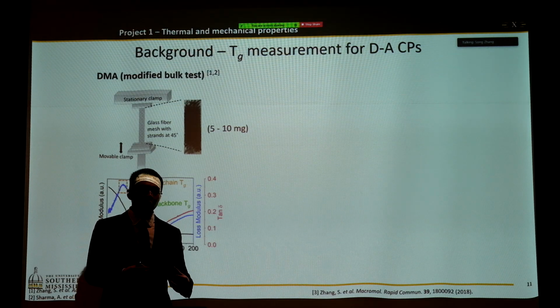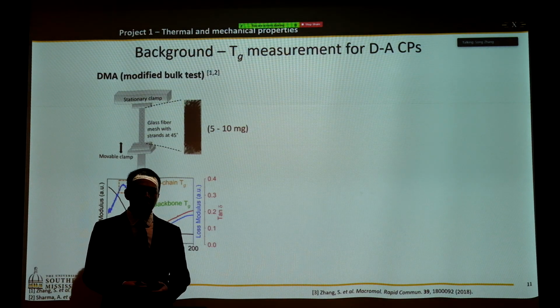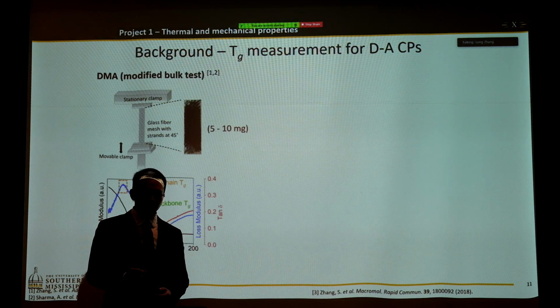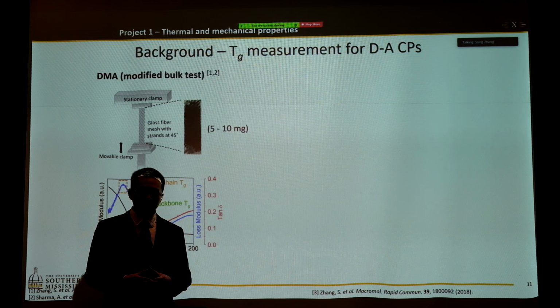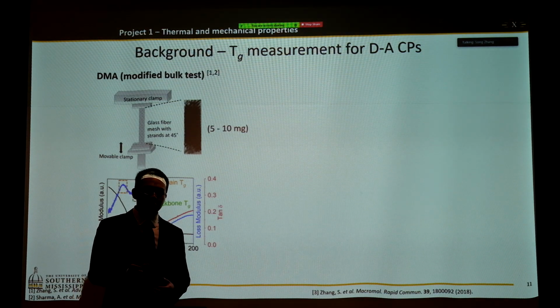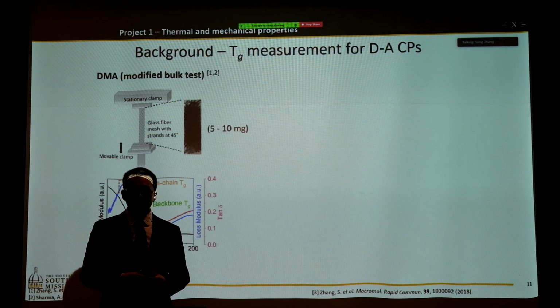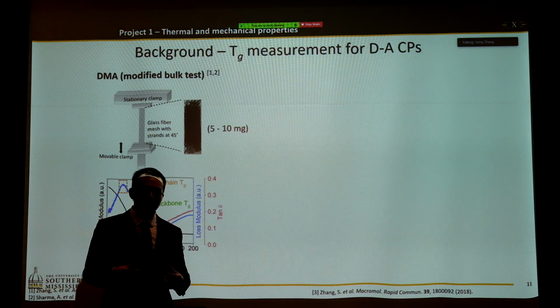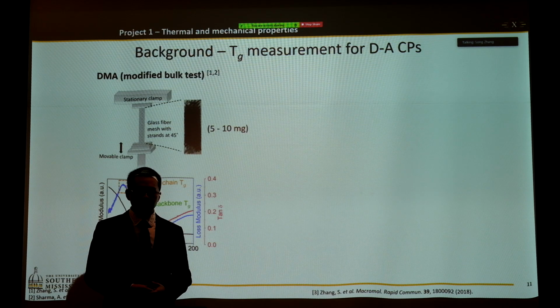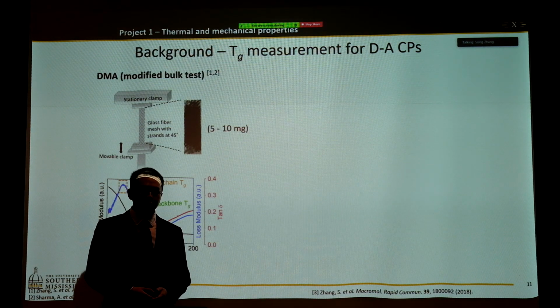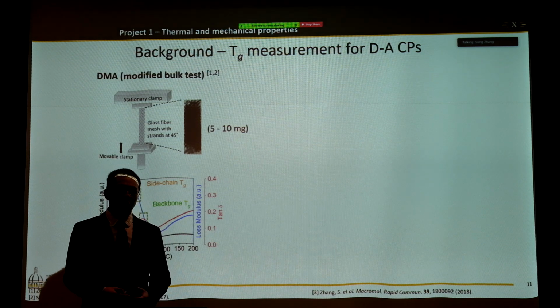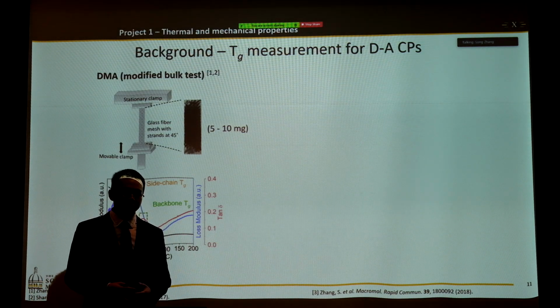to use this modified DMA measurement, where we can drop cast polymer solution on top of glass fiber. And glass fiber can provide support, and polymer is kind of a binder in between. And with only 5 to 10 milligrams of material, we can sufficiently extract the thin film Tg response from a traditional DMA test. And as shown here is a typical DMA measurement, where we have two glass transitions seen.